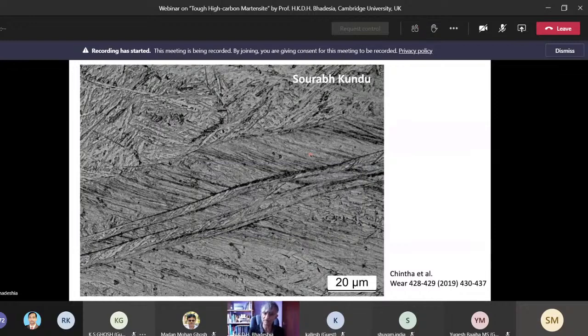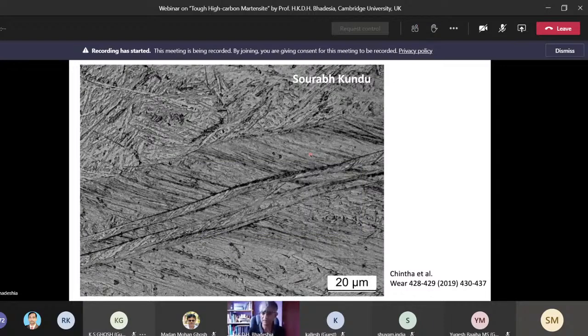So if we leave the austenite grains in a severely pancaked state by finishing the hot rolling at a low temperature, then you can achieve a coherent austenite grain size which is of the order of 0.5 micrometers. I emphasize the word coherent because martensite plates cannot cross grain boundaries. Okay, so if they meet formidable dislocation barriers, they will simply stop. So effectively, you've controlled the largest length of the martensite to be approximately 0.5 micrometers.